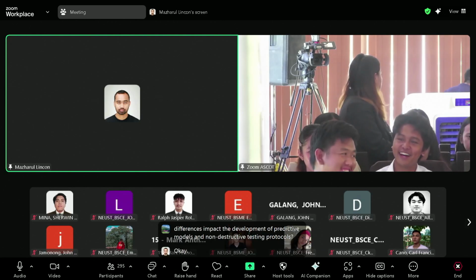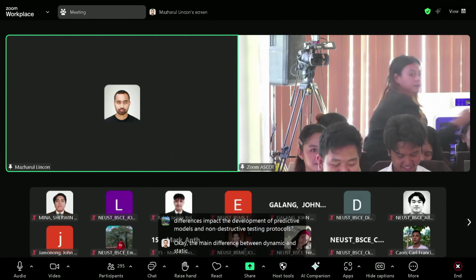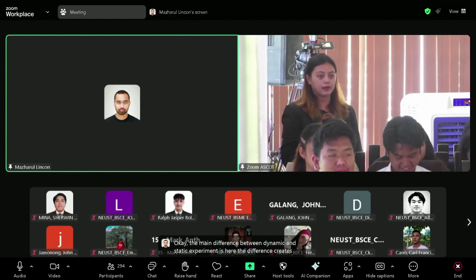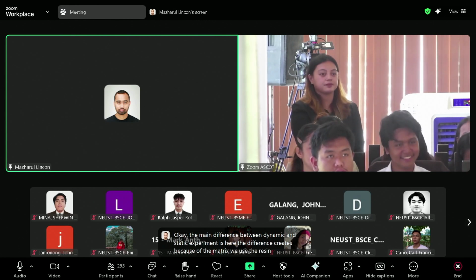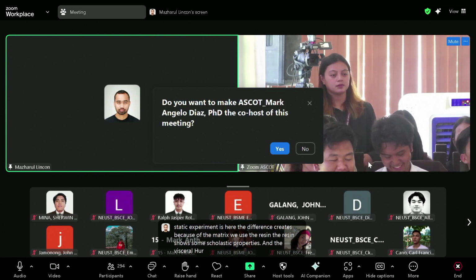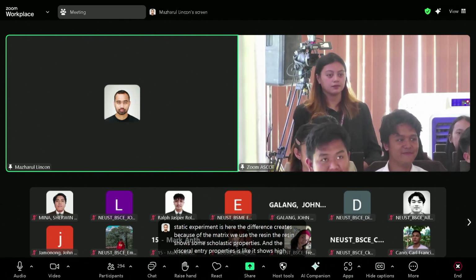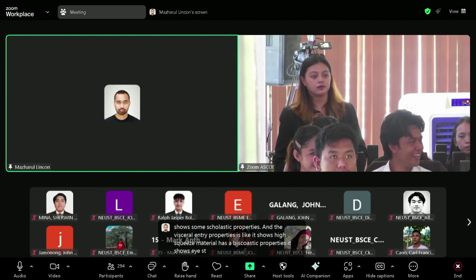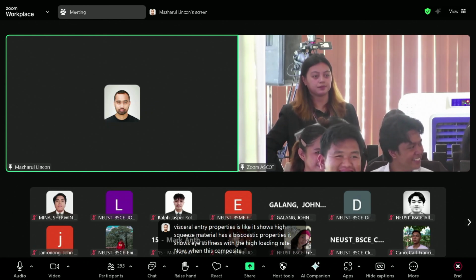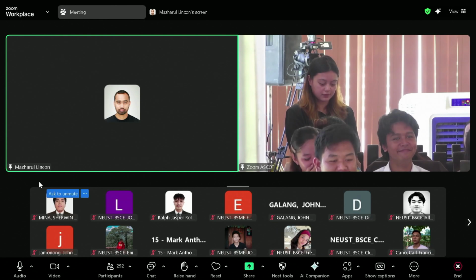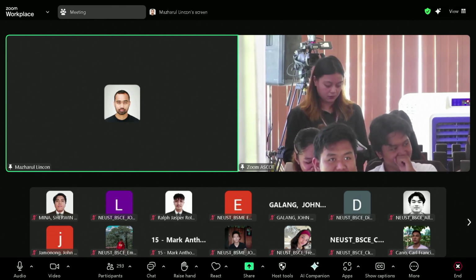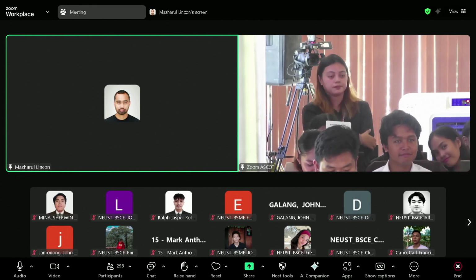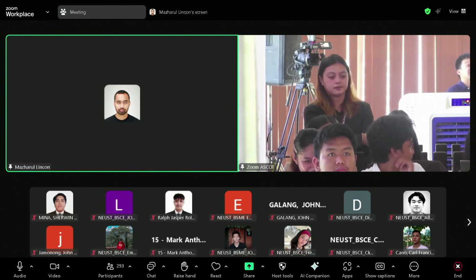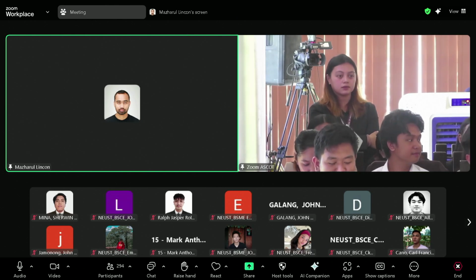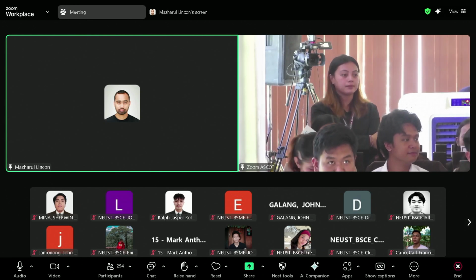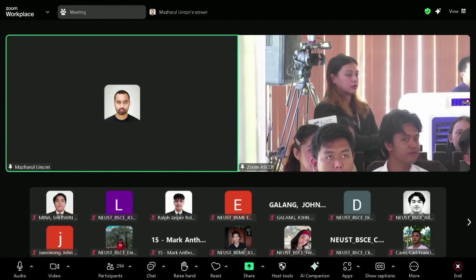Okay, the main difference between dynamic and static experiments arises because of the matrix we use, the resin. The resin shows some viscoelastic properties—like high strain rate materials, it shows high stiffness with a high loading rate. Now since this composite material is made of fiber and matrix, the composite also shows some viscoelastic properties. So when we use it in a dynamic test, it shows more strength and stiffness, or needs more force to break, compared to static, because of the matrix's viscoelastic properties. That is the main difference, and that's the main reason for doing dynamic and static tests, to see the difference between the same composite specimen.